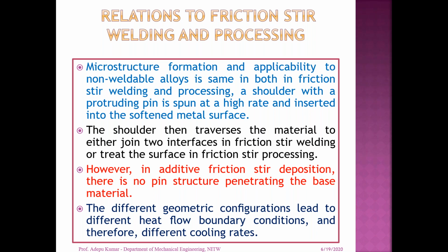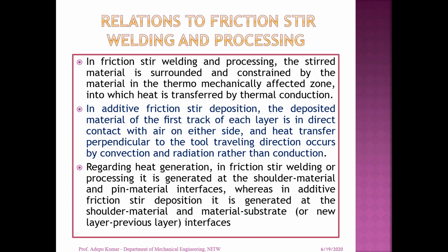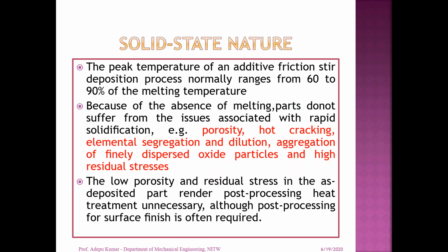So in future capabilities, the peak temperature of the additive friction deposition process normally ranges from 60 to 90% of the melting temperature because of the absence of melting. The parts do not suffer from the issues associated with rapid solidification, like porosity, hot cracking, elemental segregation and dilution, aggregation of finely dispersed oxide particles, and residual stresses. The low porosity and residual stresses in the as-deposited part render post-processing heat treatment unnecessary, although post-processing for surface finish is often required. So this is one of the papers I took from a journal paper.